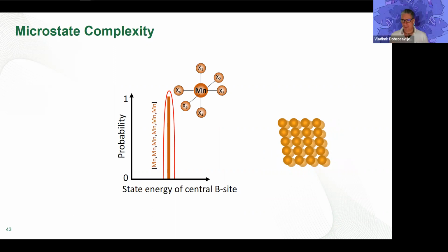But understanding before you even get to that point, lanthanum manganite in the bulk actually wants to have an antiferromagnetic coupling. You have to understand that when you make a film of that thing, it goes to a ferromagnetic coupling because of the change in the Jahn-Teller structure and what happens when you shrink it. Then when you put that next to, say, a nickelate or something else, you need to have in your mind what's really going to happen with the local charge state. And so this is manganese and nickel. If nickel wasn't in there, then how is manganese going to interact at this point?